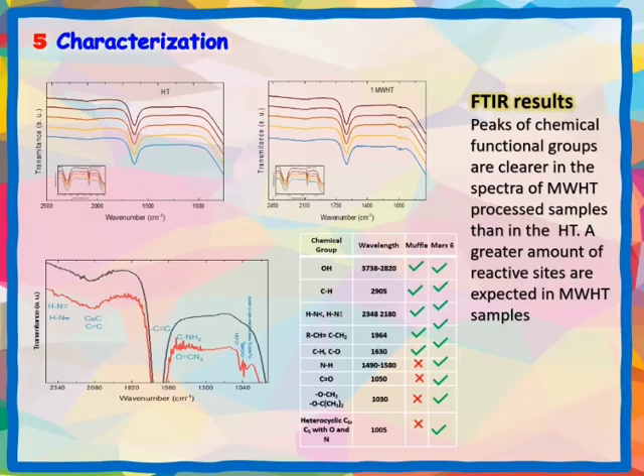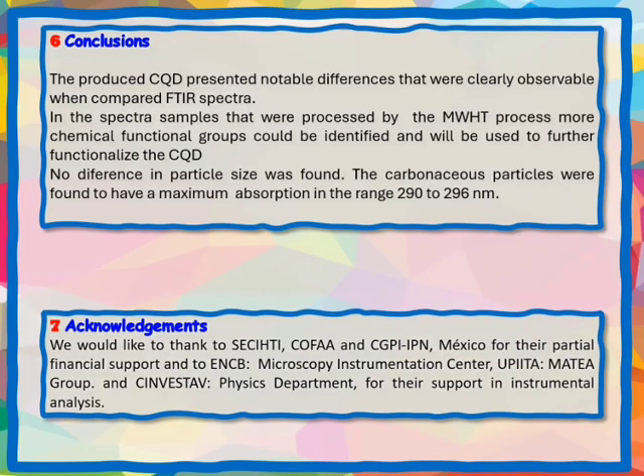The carbon quantum dots produced present notable differences that are clearly observed when comparing the Fourier transform infrared spectroscopy spectra. There are a greater number of functional groups on the surface of these quantum dots, and these will be used to functionalize their surfaces. No differences were found in the particle size distribution. The absorption spectrum showed an absorption band in the 290 to 296 nanometer range.